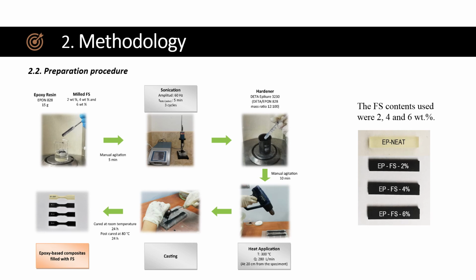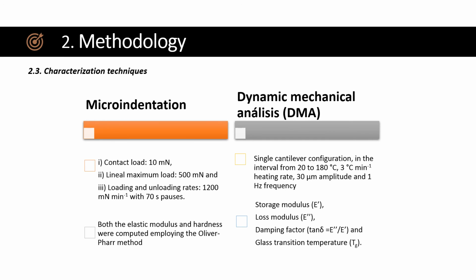Finally, the upper specimen surface was polished to improve the surface quality. The as-prepared composites were denoted as shown in the figure on the right. The control sample and composite specimens were tested through microindentation using the conditions shown on the screen. Both the elastic modulus and hardness of these composites and sample were computed employing the Oliver-Pharr method.